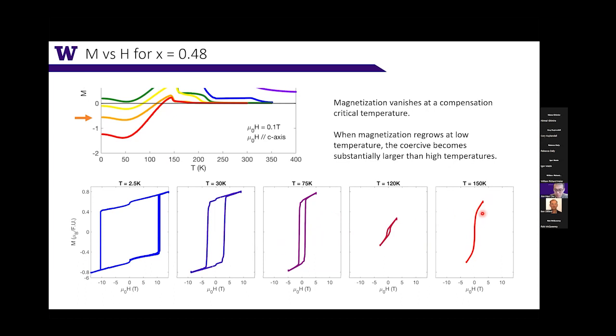When you apply a small field, you polarize the magnet so that the total moment is parallel to the manganese moments. But when the terbium moments surpass the manganese moments, you're trapped in this state and cannot overcome the coercive field. Therefore, you get a negative magnetization. Obviously you won't see that in M versus H, because with a larger field you can fully polarize it back so that the magnetization is along the net magnetization direction.